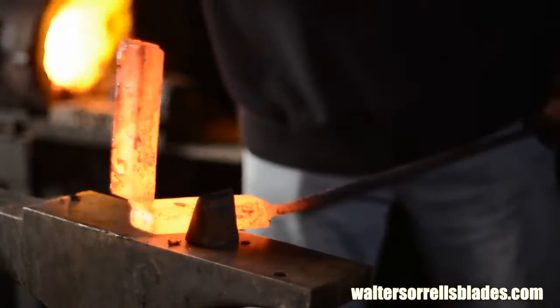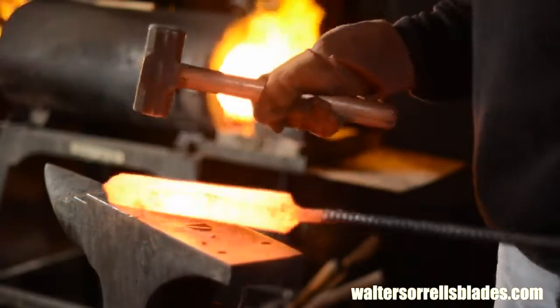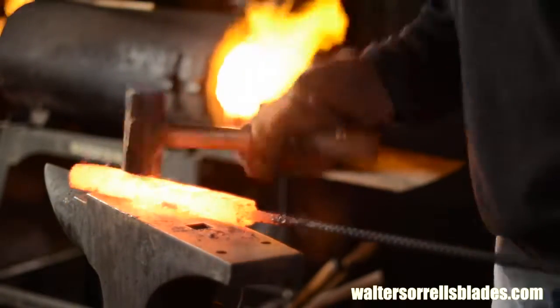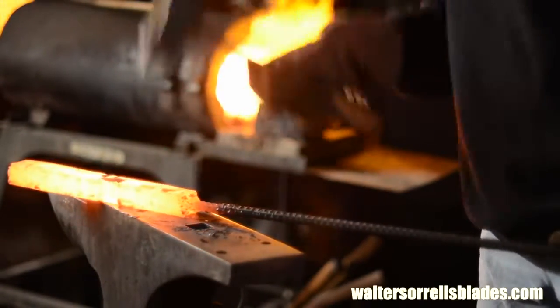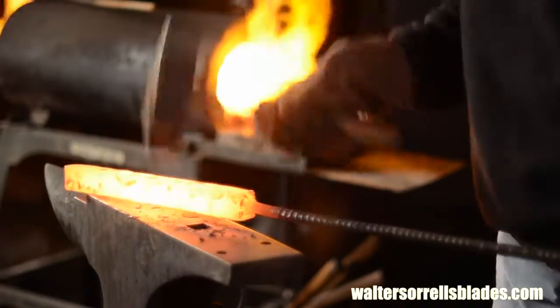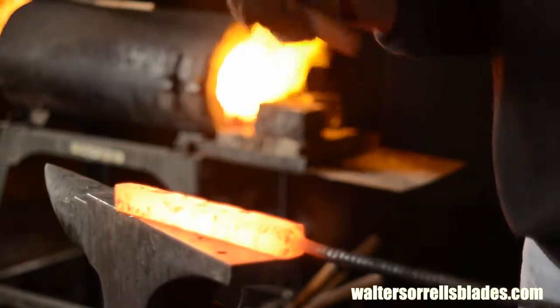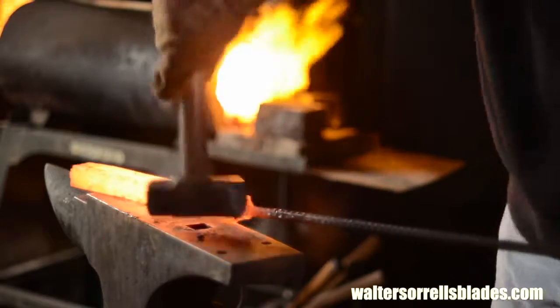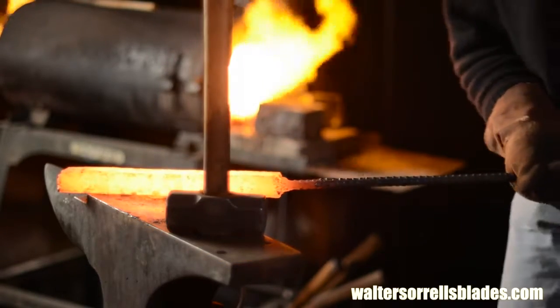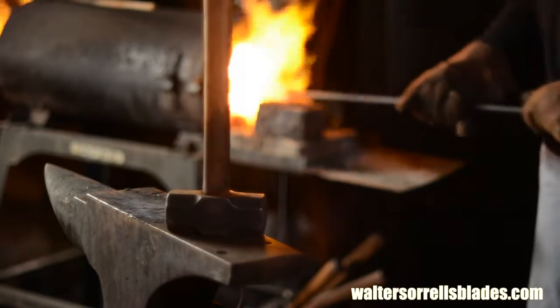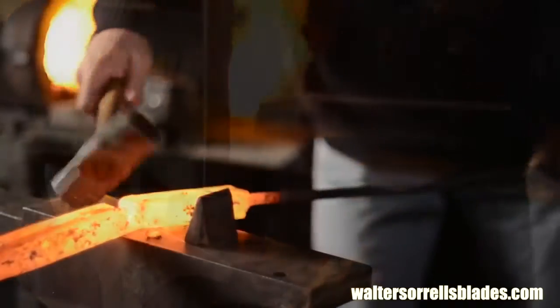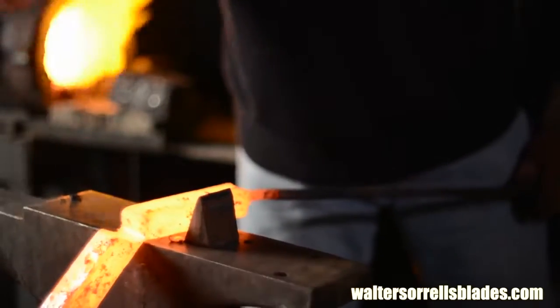Before folding, you want to do everything you can to clean the interior surface, that is, the one that you'll be welding together. So after I hot cut the billet, I'll cover it with flux and stick it back in the forge. Well before it hits welding heat, I'll pull it out and use a wire brush to clean as much scale off as I can. I don't have footage of that, but it's very simple to do.